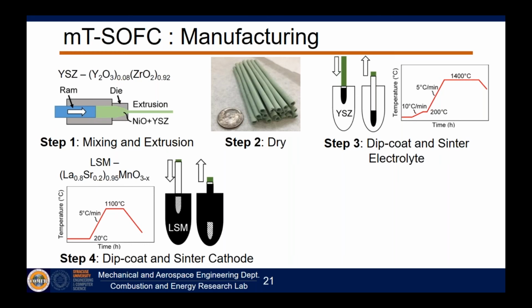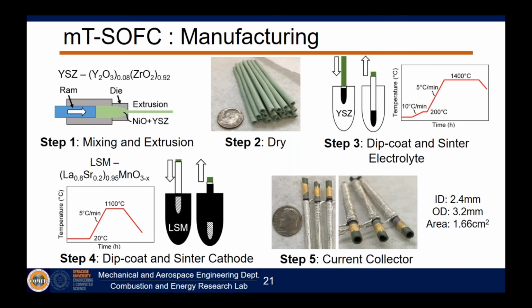And then ultimately, once we've got the cathode on, we apply what's called a current collector. We need to get the electrons on and off the fuel cell, right? And so for the cathode, we're using some silver paste here and silver wire. And you can't actually see it, but this gold is on the anode and it's directly connected to the anode. We don't have electrolyte all the way. And you can kind of get a sense of the size. If you look at the little sample that's going around, these are fairly small, right? About 2.4 millimeter internal diameter, microtubular solid oxide fuel cells.